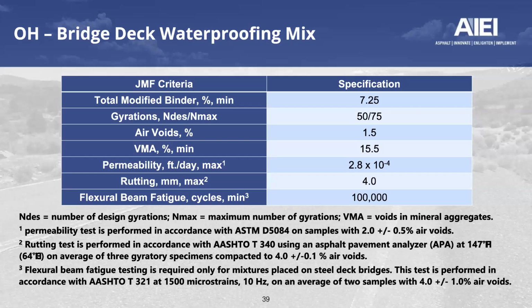They do have a permeability requirement, which in bridge decks is very common. We want to have that low permeability. Rutting is a maximum of 4 millimeters, and we can see that they are also using the APA, and the requirements you can see down below again at 64 degrees C.